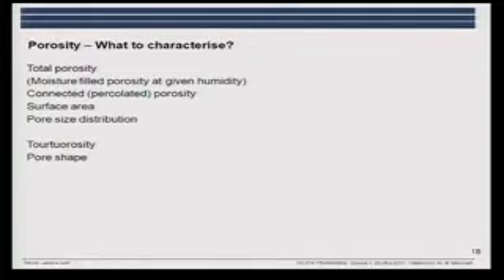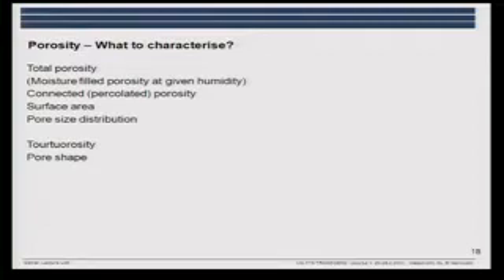So, if we just talk about the porosity, it's total porosity, we could say. And often we would look at the moisture-filled porosity at a given humidity. That, for instance, if we want to determine the sorption isotherms. We could also be interested in the connected porosity or the percolated porosity. And especially if we're talking about ingress, that's of relevance. The surface area, to describe the amount of water absorbed on the surface. And it's also an indirect way of describing the fineness of the pores. The pore size distribution could be relevant. And then the tortuosity and the pore shape.